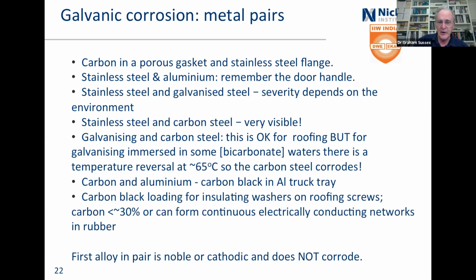And carbon black loading in insulating washers for roofing screws, tech screws they're called here. If you get more than about 30% carbon, then you can get continuously conducting electrical networks, and away it'll go. In each of these things, the first in the pair is noble or cathodic, and it's not going to corrode.